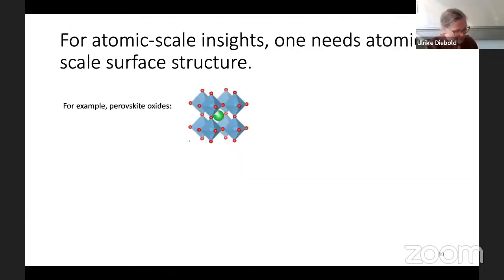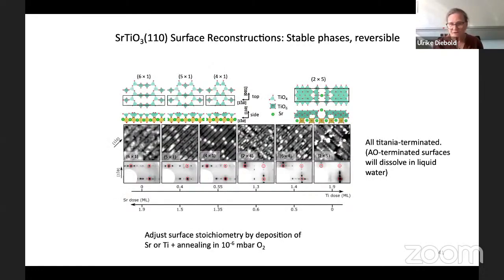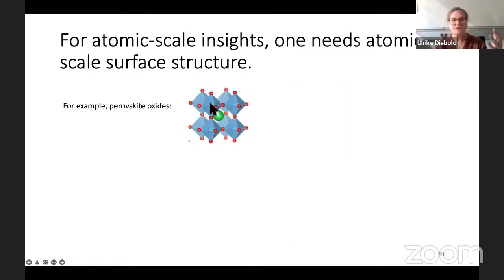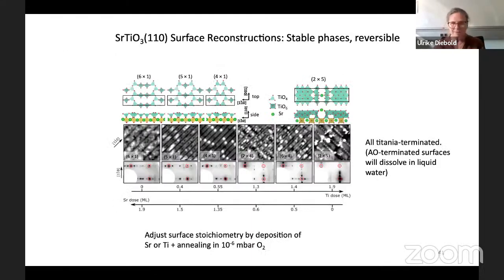For other things, when Andrew invited me, he alluded to perovskites and spinels, and we've looked in ultra high vacuum, for example, at perovskites. What we found is that perovskite structures are a zoo of surface structures. People always say, okay, you have the AO termination and the BO2 termination, and look at those, period. In reality, depending on the surface chemical potential, you can have all sorts of different surface structures. Some of them will dissolve, an AO-terminated surface dissolves in liquid water. So it's just a thing of caution.